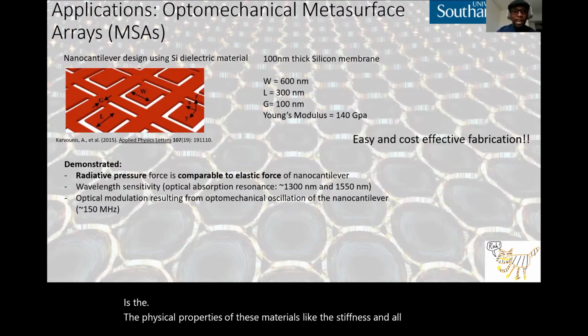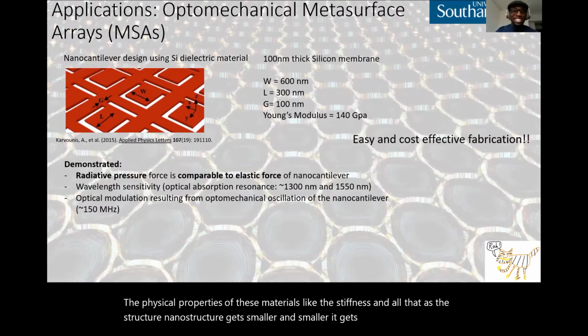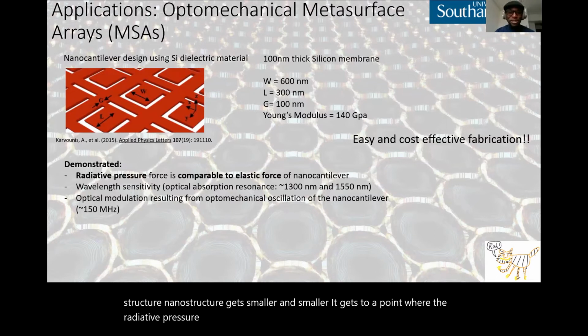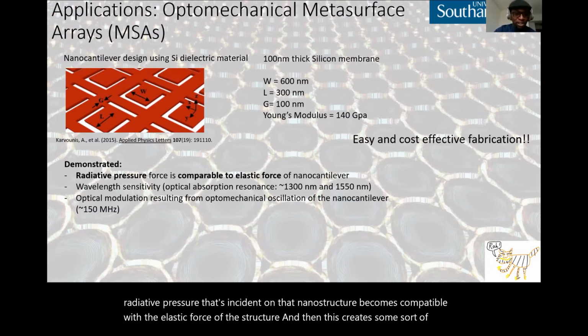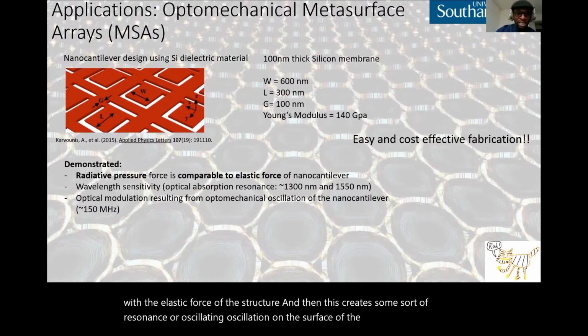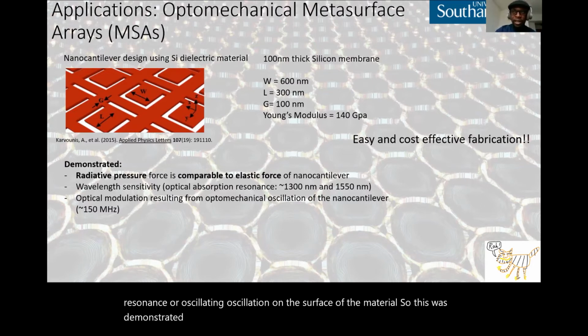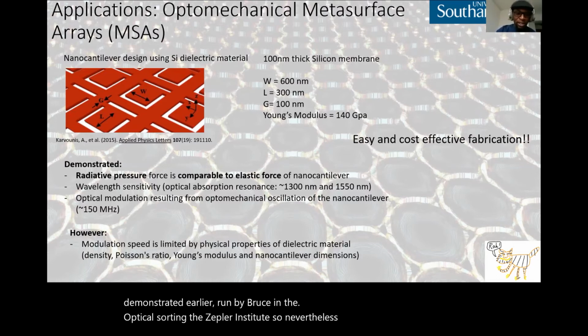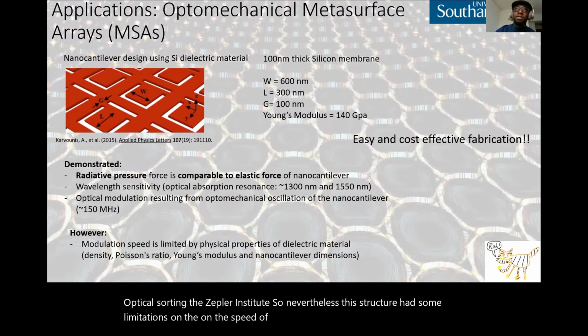So as the nanostructure gets smaller and smaller, it gets to a point where the radiative pressure that's incident on that nanostructure becomes comparable with the elastic force of the structure, and then this creates some sort of resonance or oscillation on the surface of the material. So this was demonstrated earlier on by Bruce at the Zepler Institute. Nevertheless, this structure had some limitations on the speed of the oscillation, which was within a couple of megahertz, due to the low stiffness, or Young's modulus, if you like.